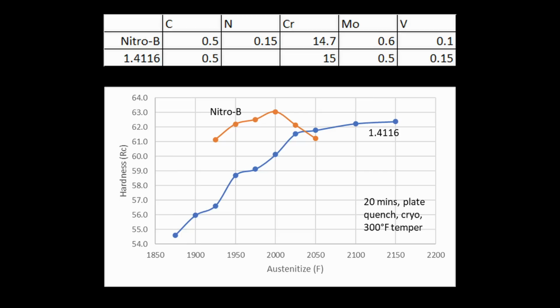Because this is really cool. When I see this, this is a steel that I don't think most people think can get to these levels of hardness. I think that for the most part, people when they see this 1.4116 steel, they think, oh, maxes out like 57, 59. You need more carbon. That's why it's not doing it. And then you're showing here, if you do the cryo with the right austenitizing temperature, I mean, we're at 62. It's not chump change for hardness.